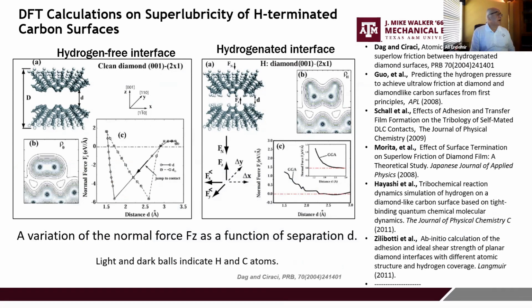If you look at a diamond 001 surface pressed against another without hydrogen present in between, as you bring these surfaces together, after a certain distance, about maybe 2.75 angstroms or so, these surfaces would actually develop very huge attractive forces, as shown on the left side of the diagram.